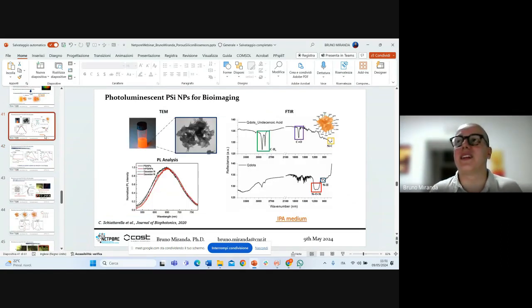It is not a covalent binding, it's just a conformation, a structural interaction. You can simply use a very basic buffer, for example sodium hydroxide. Sodium hydroxide is the one that we were using to detach, at something like 5 millimolar concentration. In this way, you see the detachment of the template from the polymer that instead remains in the porous silicon.